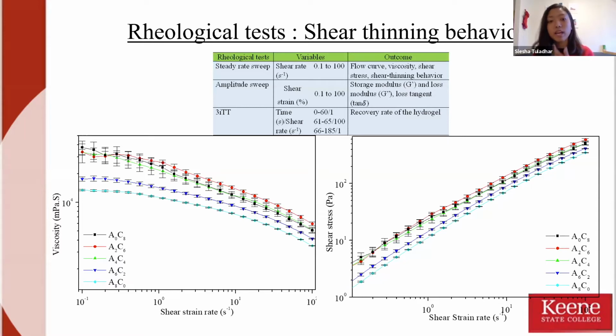And for the thixotropic test, we made sure that we took 3 intervals of time, which helped us know how the biomaterial is going to heal after it shows the shear thinning behavior. So on the graphs, we can clearly see that the materials are showing shear thinning behavior. It is exactly what we wanted, and that is what the graphs are showing.